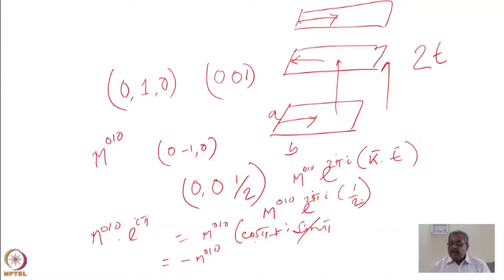But in reality, it is a simple picture. There can be more complicated magnetic propagation vectors. Sometimes it may even require thousands of lattice planes. And there are cases where the structure is commensurate with the crystallographic structure. That means I start with one crystallographic lattice plane with a certain magnetic moment in a certain direction. After an integral number of lattice planes, I'll come back to the same moment, which will match with another lattice plane, maybe several or thousands of lattice planes away. In case of an incommensurate structure, which is a more complicated problem, the magnetic structure is not commensurate with the crystallographic lattice structure, and there will be some gap.